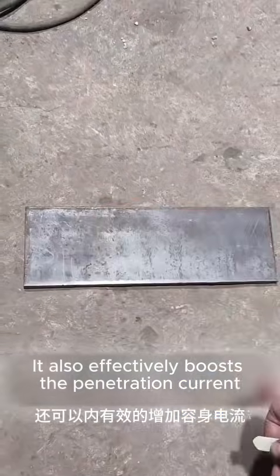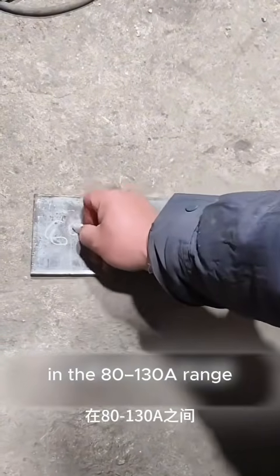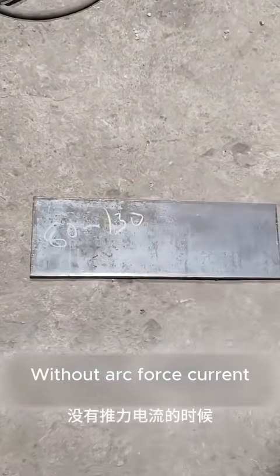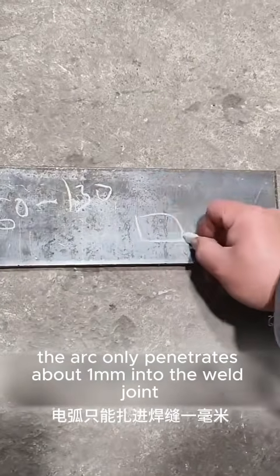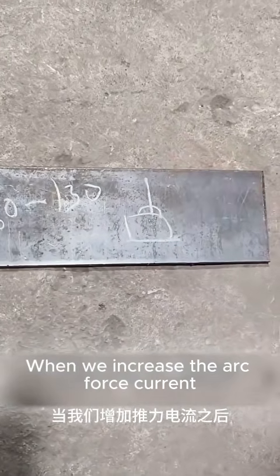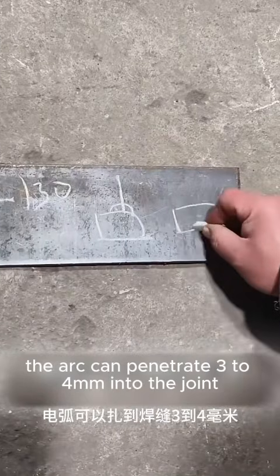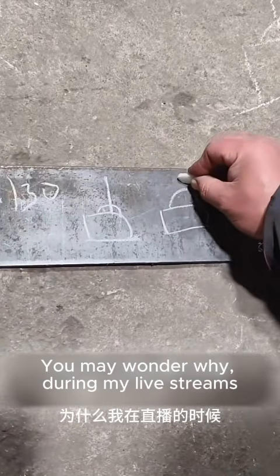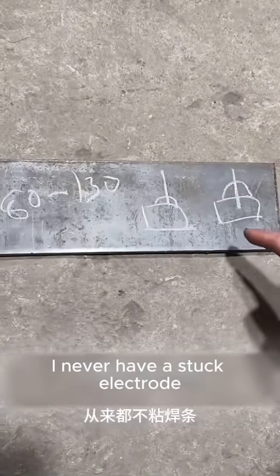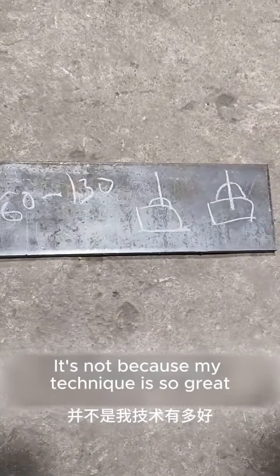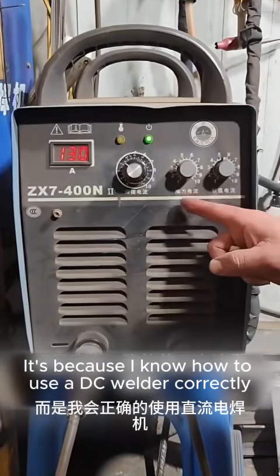It also effectively boosts the penetration current in the 60-130A range. Without arc force current, the arc only penetrates about 1 millimeter into the weld joint. When we increase the arc force current, the arc can penetrate 3 to 4 millimeters into the joint. You may wonder why, during my live streams, I never have a stuck electrode. It's not because my technique is so great. It's because I know how to use a DC welder correctly.